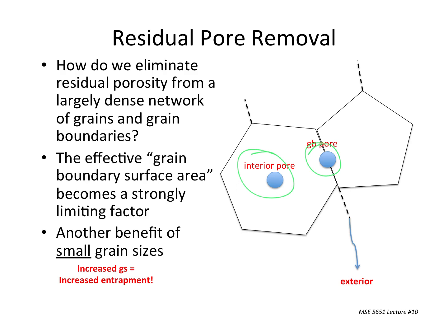All right, and so again, think about this as grain boundary surface area, and this is again another benefit of small grain sizes. If we can keep our grains submicron, then this whole process of eliminating pores becomes much more efficient, meaning that our defects become smaller or hopefully absent, is where we're really driving at. No pores at all. In most cases, they're not successful, but you make the pores small when you make the grain sizes small, and you try to resist this process of grain growth, which is fighting us in terms of our desire to get away from this entrapment issue, pores on the inside of the grains. All right, any questions about that?